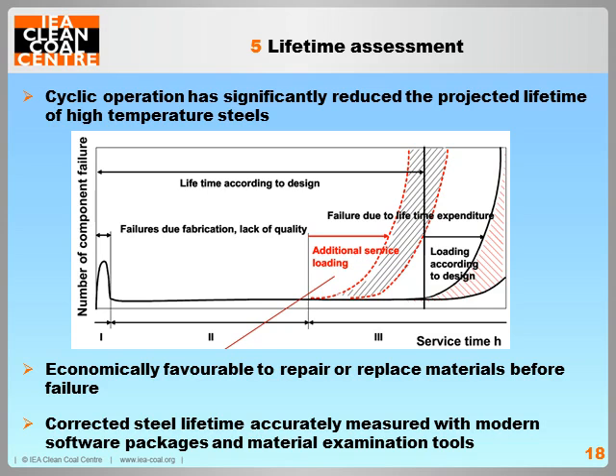If pulverised coal-fired power plants are cycled beyond their design specification, then there is a high chance of failure, such as type 4 cracking or dissimilar metal weld cracking. This figure shows the relative lifetime decrease for high temperature components with the introduction of cyclic operation.